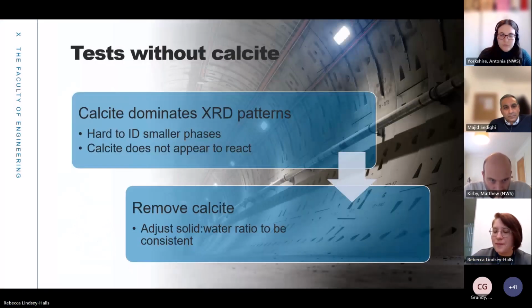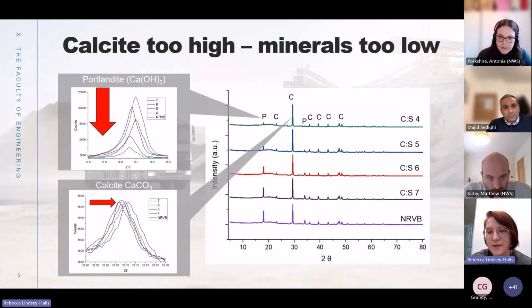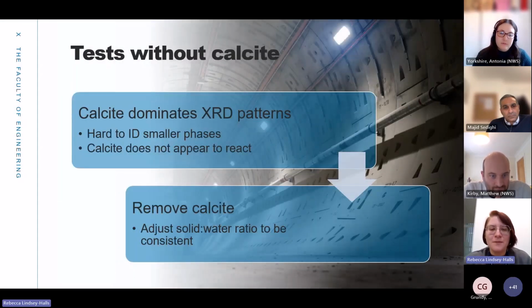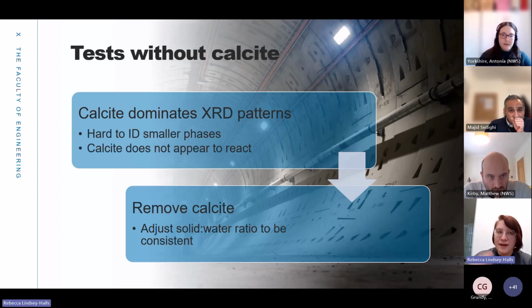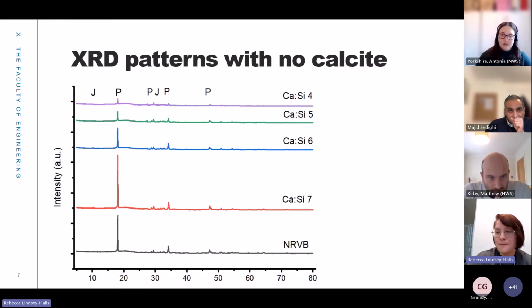So this shows that the calcite is dominating the XRD patterns and making it very difficult to identify any smaller phases. If I just go back, you can't really see any other peaks, and you definitely can't identify them accurately. But also the calcite doesn't seem to be reacting. So I thought the solution to this was to remove the calcite, but then adjust the solid to water ratio so it's consistent, so it's still representative. However, because the portlandite is reacting, it needs to stay.